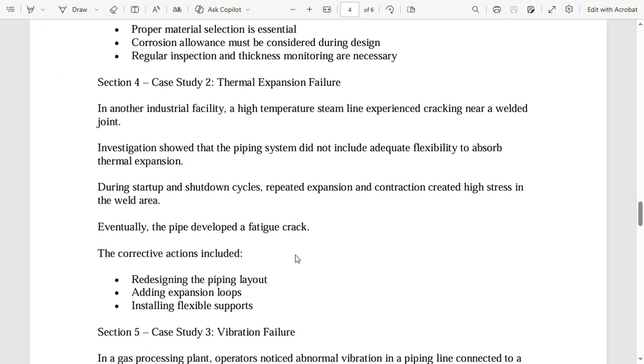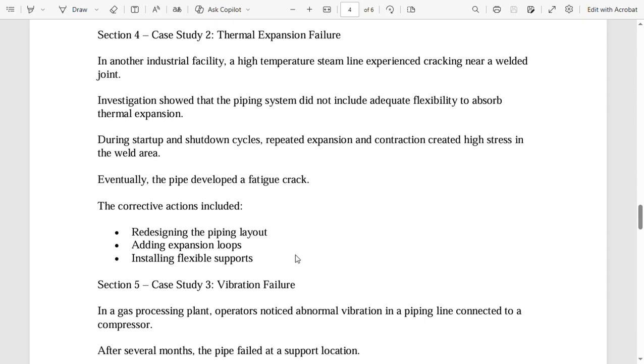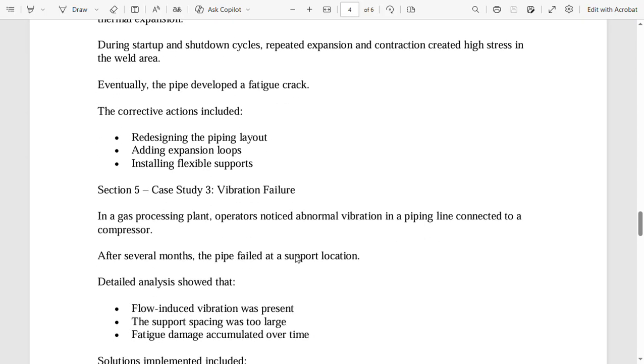Then next is the case study on thermal expansion failure. In another industrial facility, a high temperature steam line experienced cracking near a welded joint. Investigation showed that the piping system did not include adequate flexibility to absorb thermal expansion. During startup and shutdown cycles, repeated expansion and contraction created high stress in the weld area. Eventually, the pipe developed a fatigue crack. The corrective actions included redesigning the piping layout, adding expansion loops, and installing flexible supports.